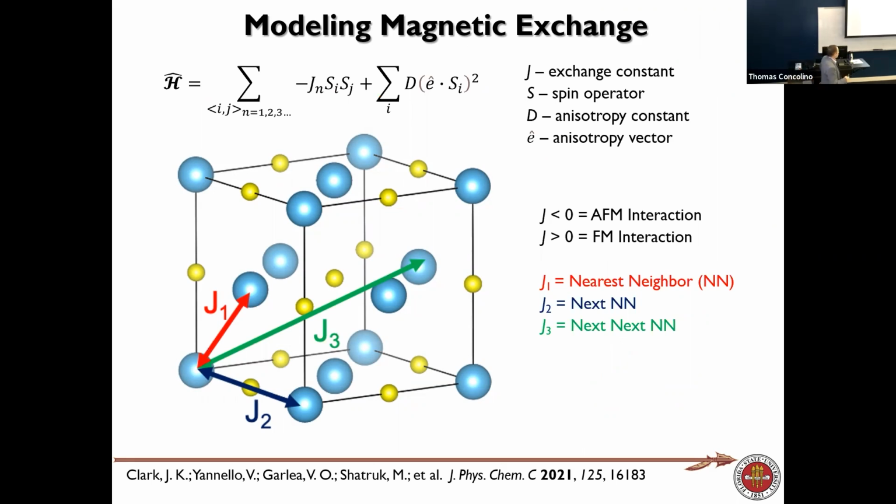And the reason this happens is because you're moving the manganese atoms further apart, so you're decreasing this direct interaction, but you have very strong superexchange across the sulfide bridge due to strong covalence in this bond. So you have quite a lot of spin density delocalization onto the sulfur, and that really strengthens the exchange between manganese atoms across this 180-degree sulfide bridge.